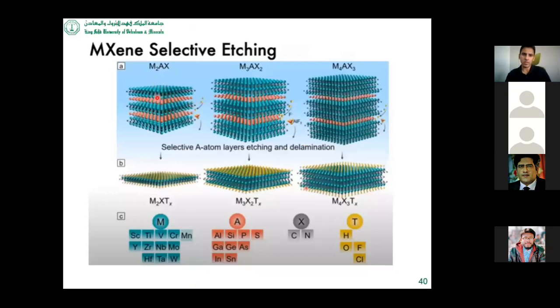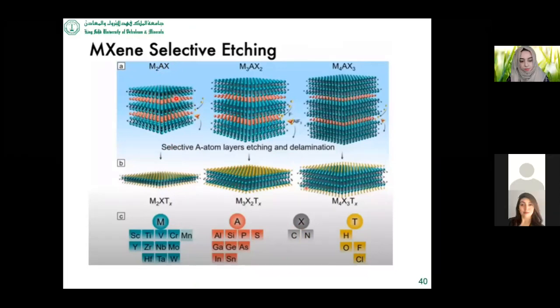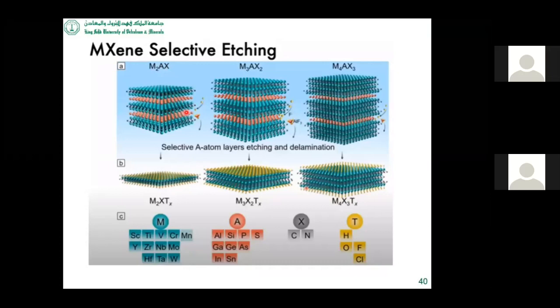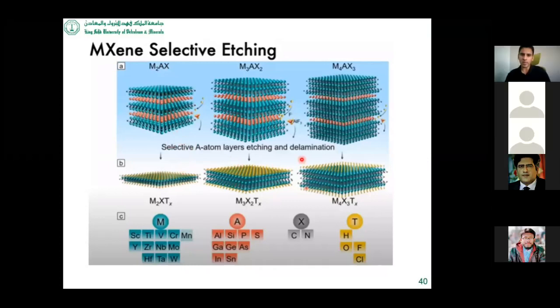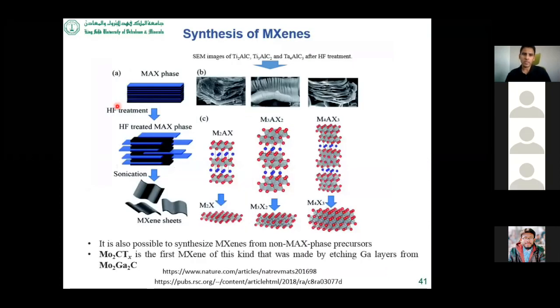So this is how MXene can be produced. You can see here the MAX phase contains the transition metal and the carbon, as well as the A layer. This is the M element, this is the A, this is the X, which is carbon or nitrogen, and this is the surface functionality. By selective etching, you can remove this aluminum layer, or A layer. It can be silicon or anything else, but most commonly it is the aluminum layer. It can be removed, and later by delamination you can separate these sheets. If you are able to separate these sheets, you will get some very attractive features for various applications. So this is how MXene is produced.